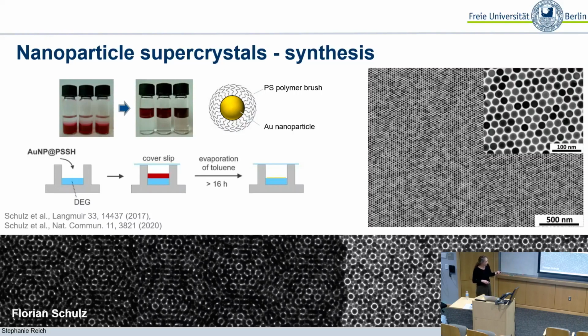So this is how these monolayers are produced. That's kind of shown here. They are grown at the interface between two liquids. So you have one liquid down here where the gold nanoparticles cannot be dissolved. And then you put toluene with the gold nanoparticles on top, and you slowly let the toluene evaporate. So the concentration of the gold nanoparticles keeps increasing.